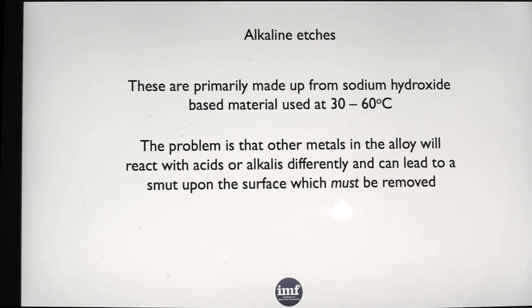Now, if we take copper and aluminium, the aluminium dissolves beautifully. You'll be left with a nice white aluminium, looks lovely. The copper, unfortunately, reacts with the caustic to form copper oxide, which is black. So some products that have a lot of copper in, when you've etched them in alkaline etches and you take them out, they've gone from a lovely white to a deep black colour.